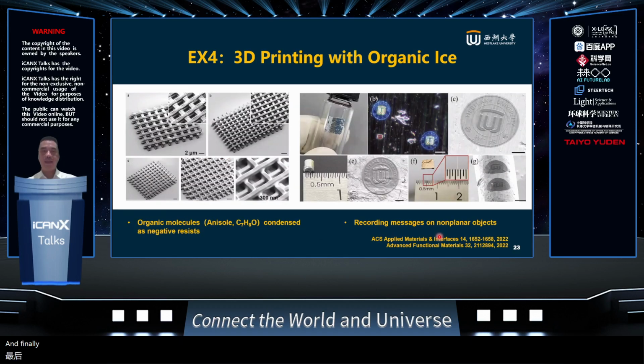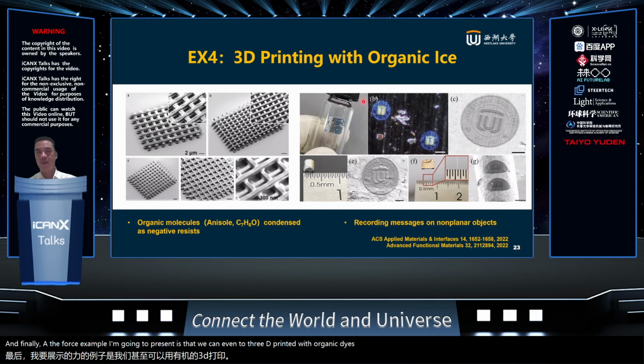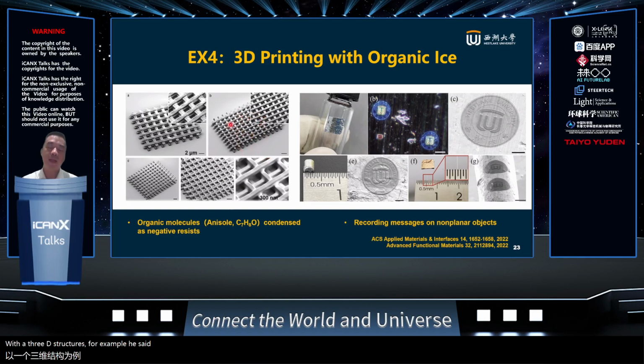And finally, the fourth example I'm going to present is that we can even do 3D printing with organic ice. That means if we use organic molecules instead of water molecules, like anisole, which is actually a liquid, and we make them evaporate and then condense again on a cold surface, through our ice lithography process, we can make very complicated 3D structures. For example, this layer-by-layer structure. Actually, we can make almost any structure out of this, and we can also make them on any surface. This is one example of a curved surface, where we can make a very nice picture on top.